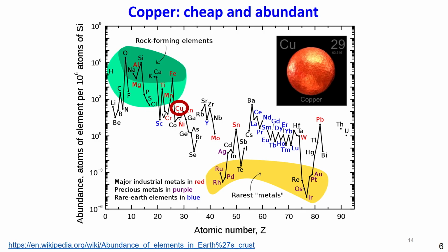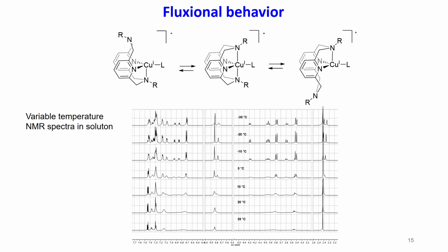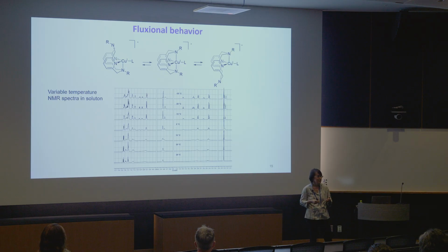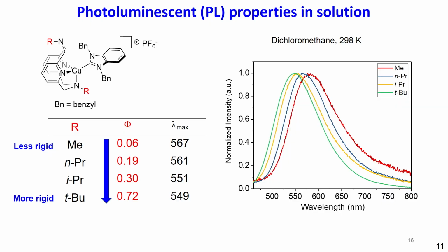So one of them is that when we make copper complexes with this ligand in model systems, we see they are actually very dynamic, very fluxional. So in solution, they easily change conformation. So these nitrogen tails are basically just wiggling up and down all the time. How do we know it? Because we can record the NMR spectra at various temperatures, and this dynamic behavior and exchange results in a signal broadening. Now, the second interesting property of these complexes, they are photoluminescent.